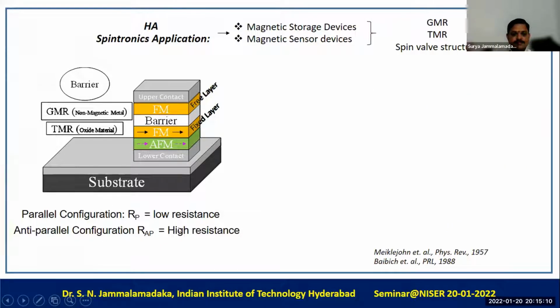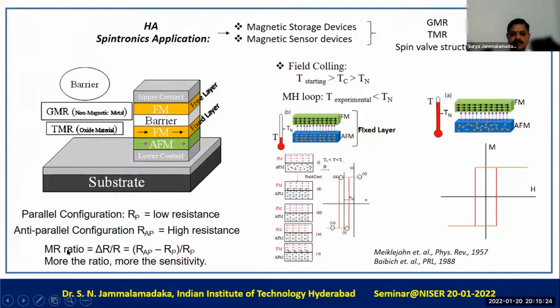So if you look, if the orientation of the magnetic moments in both ferromagnetic layers is parallel, we call it a low resistance state. If it is anti-parallel, we call it a high resistance state. And the corresponding magnetoresistance can be defined as (R_AP minus R_P) divided by R_P. If the magnetoresistance is very high, the sensitivity of the device will also be very high. Suppose you get 1000% GMR or TMR, the amount of magnetic field that you can detect will be very high. The sensitivity of the device will be very high.